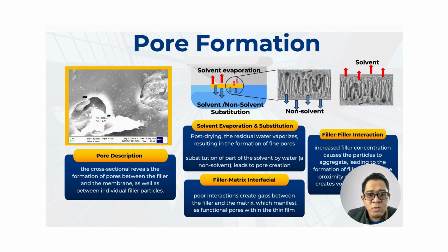And then we go to the pore formation. From the FESEM micrograph, we can see that the cross-section reveals the formation of pores between the filler and the membrane as well as between individual filler particles. And then the pore formation in ENR PVC cellulose grafted PMMA can be attributed to three principal mechanisms.